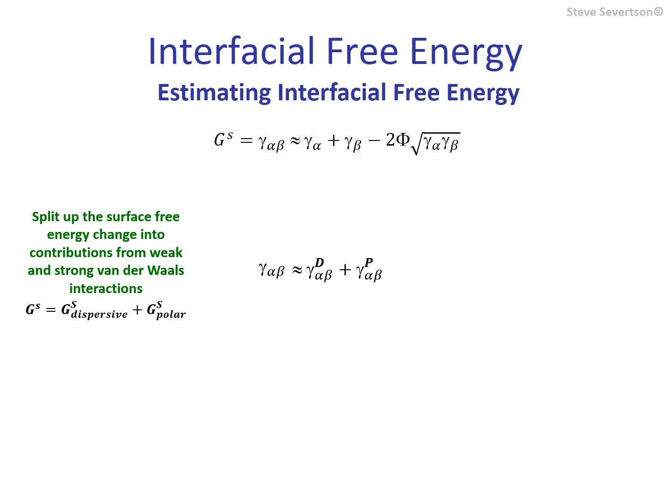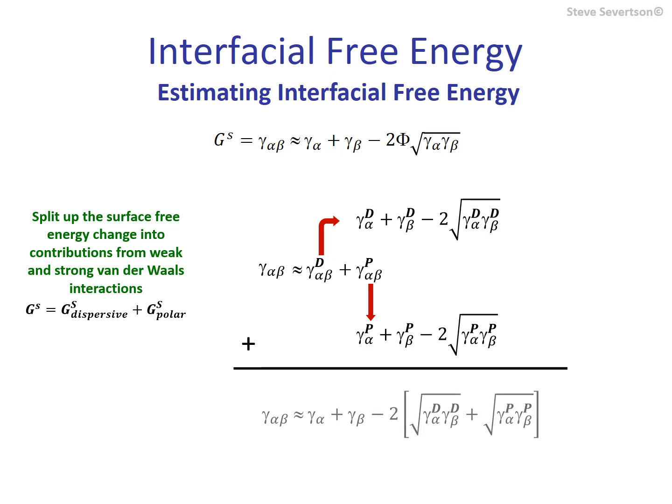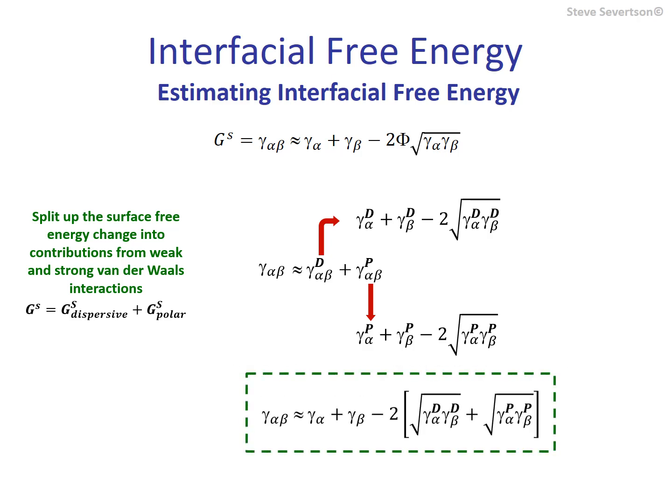Let's put what we're doing into perspective. The interfacial free energy is the change in free energy with the expansion of the interface. We can think of it as a single molecule from each of the contacting phases leaving their bulk regions and meeting at the interface, similar to a process such as a chemical leaving a pure phase and moving into a solvent. We split up the free energy into contributions from assumed independent interactions. As independent contributors to free energy, the interfacial equation applies to the dispersive and polar free energies.